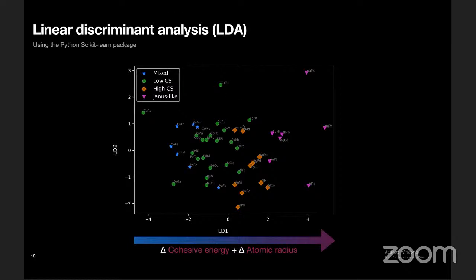So here, each data point represents each bimetallic combination, and they are color-coded based on the equilibrium structure found by MD and Monte Carlo. We can see that the first axis explains the pattern quite well, because on the left side of the axis, we see more mixed structures, and as we move to the other side of the axis, we see more highly segregated structures like high core-shell structures and Janus-like structures.